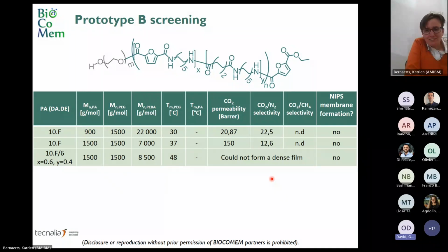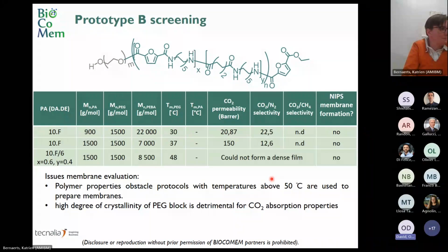Yes, so we did manage to make some films. Even if they were not mechanically very stable, we could carefully manipulate and characterize them. Once they are placed in the permeation cell, we could make some characterization. So they do have some membrane properties. They have some selectivity, carbon dioxide to nitrogen, of 22 and 12. But basically, we could not make a porous structure. So these are not useful for membrane applications.